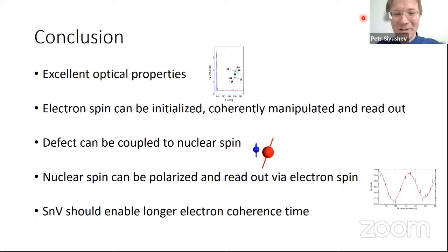Because they really managed to prolong the coherence time to tens of milliseconds, and there are some technical challenges associated with the control of the electron spin by the microwave field, especially in the dilution refrigerator, where the cooling power is really low compared to, for example, a normal helium-4 cryostat.